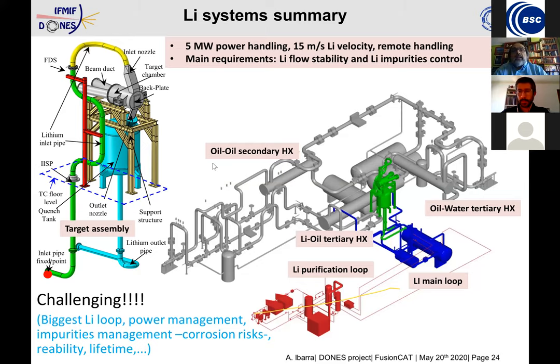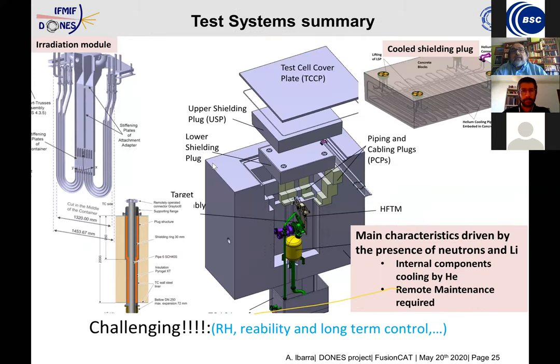Then we have the other area, the irradiation area. In this sketch, you can see where the reactions take place. The purple thing is the tubes, the accelerator tubes that transport the beam. Then the lithium loop is this green component here, together with the yellow quench tank. So the lithium is moving fast here. We have the deuteron beam hitting the lithium, and then the neutrons are produced.